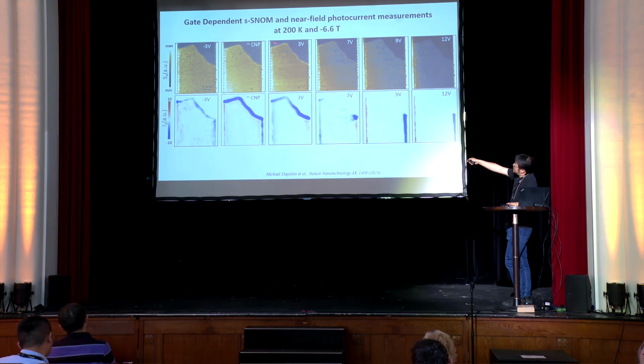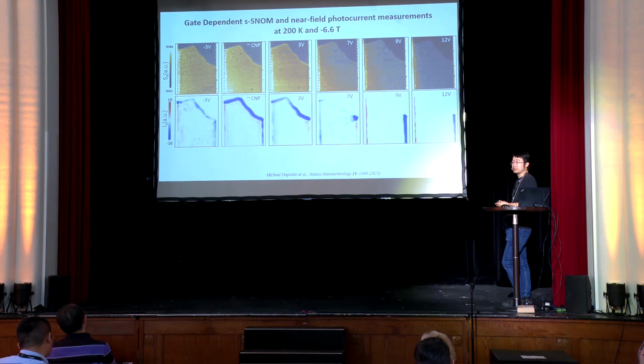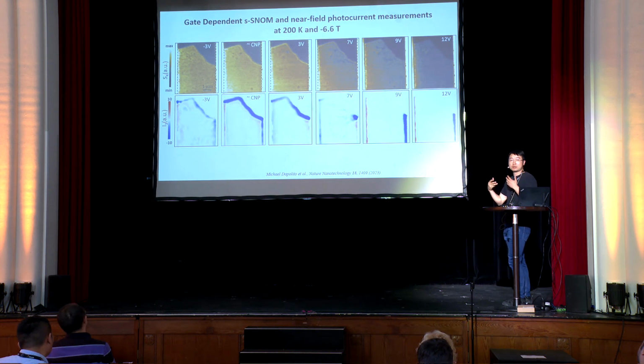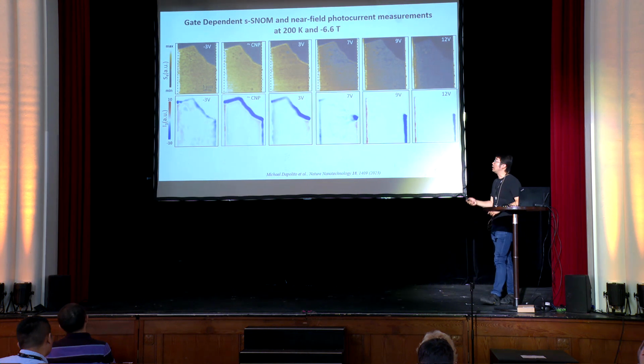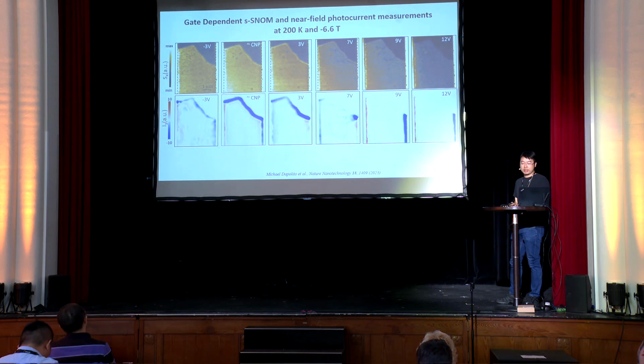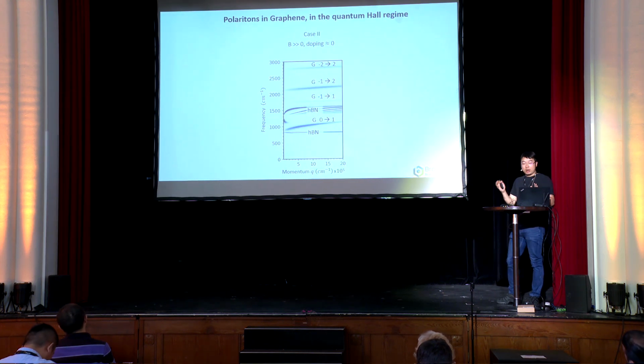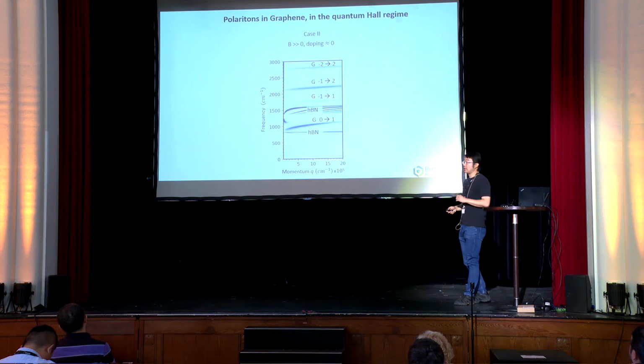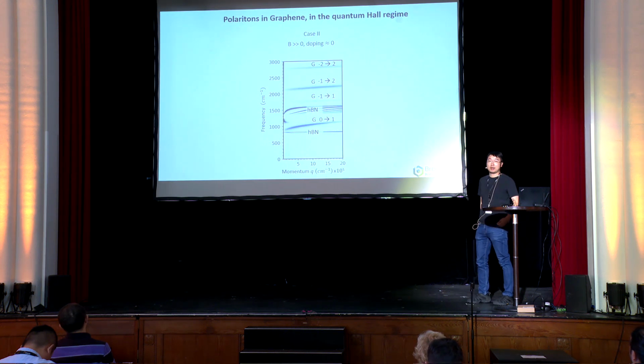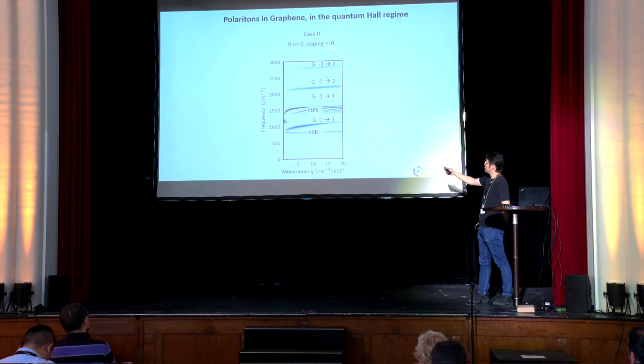And you can see, even with this projector, you can see a bright edge here. This is actually exciton magneto-polaritons. In some samples, we see one fringe, and in some samples, we see two fringes, so that we can have a full map of the dispersion of these magnetoplasmons or magnetoexcitons within our sample. But I will not discuss that. I will instead discuss how we detect these other magnetoexciton excitations with hybridization to hBN.